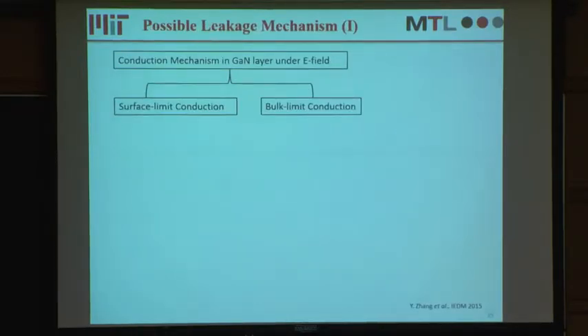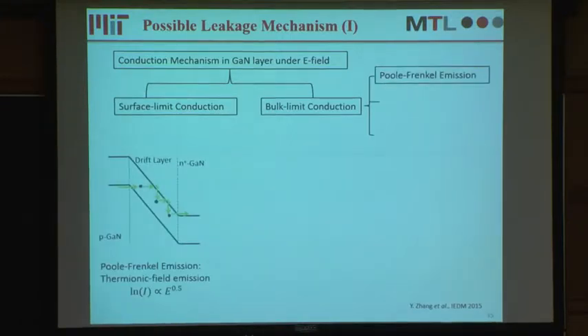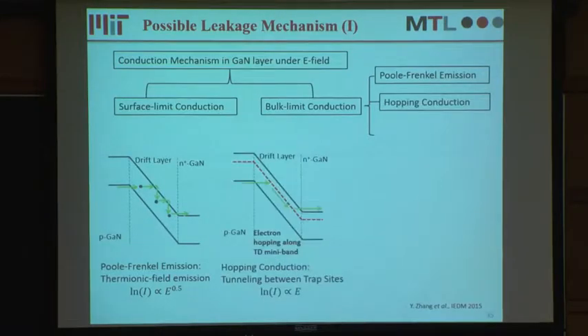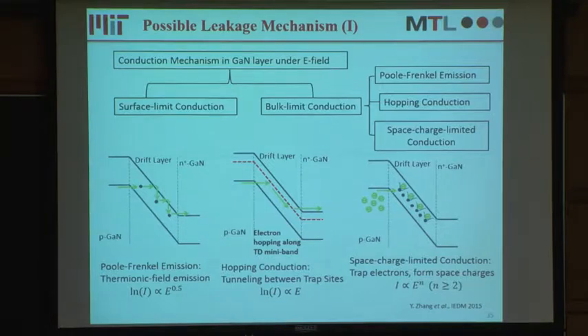So for this bulk-limited leakage conduction, we look at several possible leakage mechanisms. That includes Poole-Frenkel emission, which is thermionic field emission, and also some hopping conduction, where the carrier would do tunneling between the traps and dislocations in this drift region, and also some space charge limited conduction.